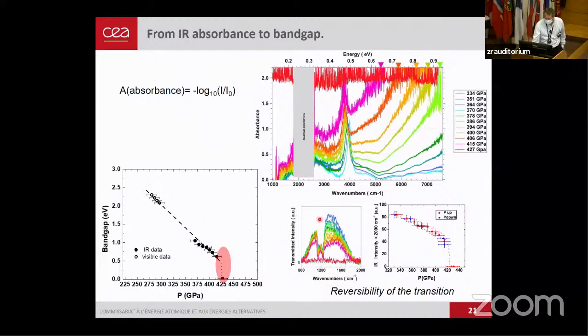Probably we cannot remove this possibility of a very small direct band gap, but we have a transition. And what's very important here is that at small wave numbers, the evolution of intensity is rapid, and we have no sign of an indirect gap coming in. So the semi-metal is taking over. We have a change in the direct gap only. And the measurement is reproducible. If you decrease the pressure, you recover the same measurement.